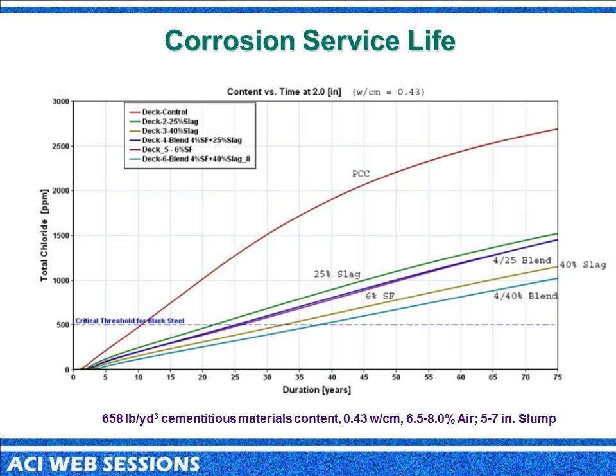So we see this as a really nice opportunity to perhaps remove some of the issues we might have at concrete production and balance it also with some of the properties, both on the plastic side and on the hardened side. Similarly, if we go to 40% slag, we see even lower, and longer term to corrosion, which would be at about 33 years. And certainly with our 4 and 40% blend, as we would expect, is our top performer.